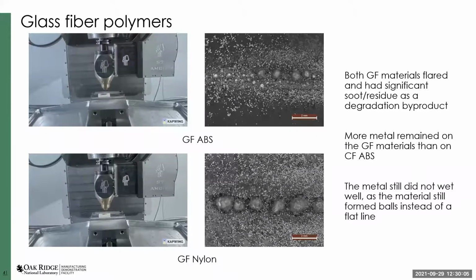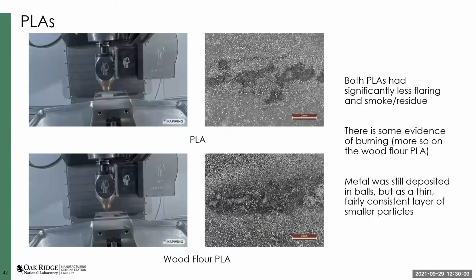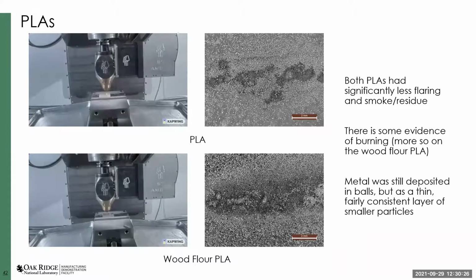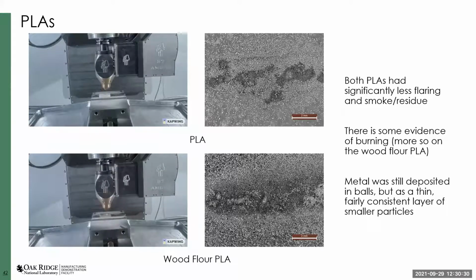All right. And then I also tested one unfilled PLA and one PLA that was filled with wood flour. I was a little nervous about that one, potentially having a thermal excursion, but it surprisingly didn't. We actually got less flaring with these two tests than with the ABS, which indicated that we're actually seeing more melting of the material than degradation of the material.